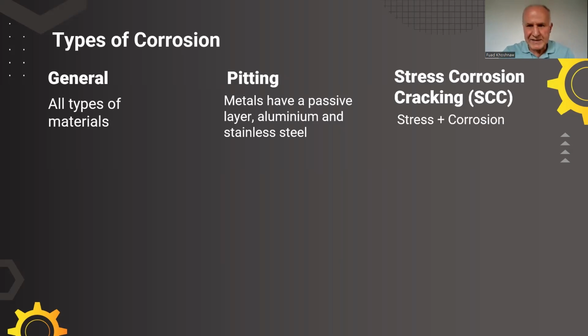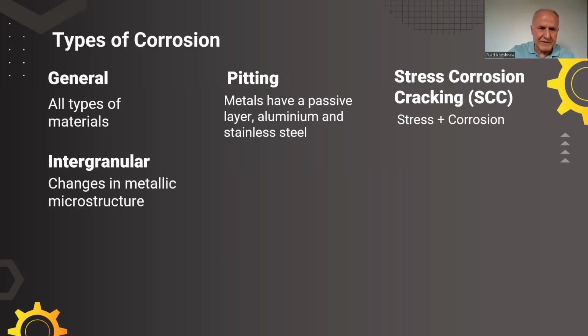Stress corrosion cracking, as the name says, is stress and corrosion. This can be static, and at that time we call it stress corrosion cracking, or it can be cyclic, and we call it corrosion fatigue. Intergranular corrosion, we will go deep into that in the next slides. It correlates with specific microstructure, when it goes through different heat treatments or welding at high temperature, which causes changes in the phase transformation and the microstructure. So it is not the same as received before. A change happens, and this change causes corrosion.